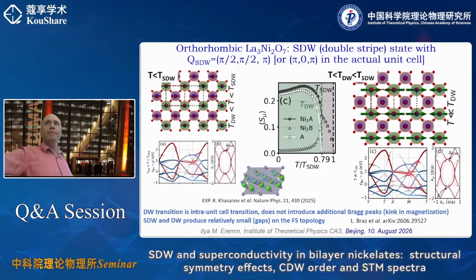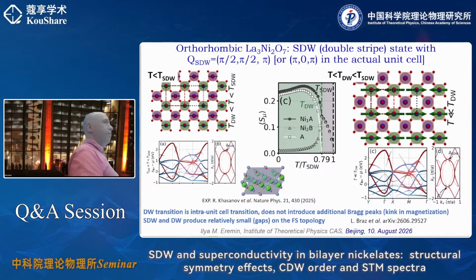So I think this charge order is kind of an induced order, right? Because you have a spin order, and the double Q of it gives the charge order. If it's an induced order, I would think it will somehow show up at the same temperature. Well, it can, but it doesn't have to. There is no symmetry argument why they should appear at the same time. But if they appear at the same time, then very likely it will be a first order transition, because once they are coupled, it will give rise to a weak first order phase transition.